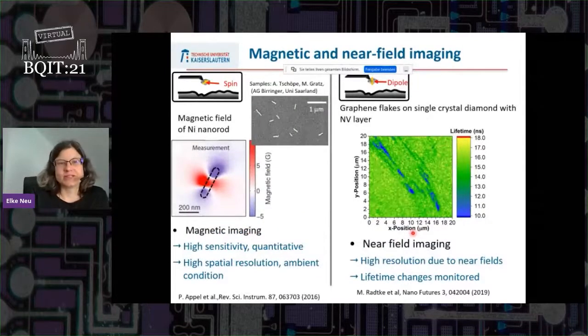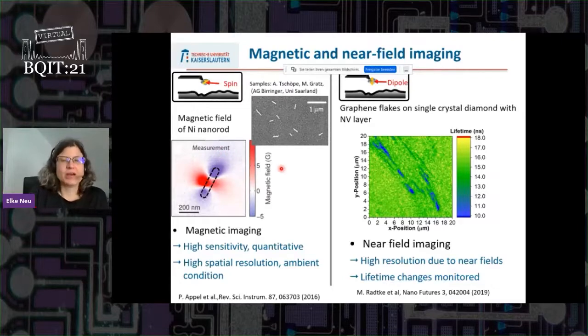Let me give you two illustrative examples of those two imaging modes or sensing modes. One is given here. You can see here the magnetic field of a nickel nanorod, which we have imaged with such a scanning NV tip. You can see we get a quantitative imaging, and we see here a quite high resolution. You can see changes of the magnetic field within approximately 10 nanometers. On the right part of the slide, you see a very simple example of such a FRET transfer. We put some graphene onto a diamond with a layer of NV centers, and you can see the excited state lifetime of the NV centers is reduced in areas with the graphene, and this is due to the fact that the energy flows from the NV center to the graphene, and this is an example of such a near-field transfer.